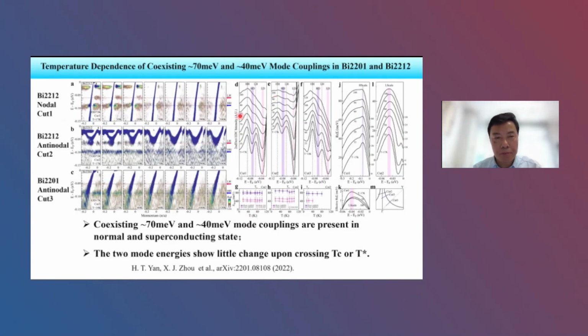Then we come to the temperature dependence. We also did this temperature dependence in Bi2212 and Bi2201 along different momentum cuts. What do we see? We warm up from low temperature to high temperature above Tc, or even above T star, the so-called pseudogap temperature. And we can still see that these two modes above Tc still exist. So the coexisting 70 millivolt and 40 millivolt modes are present not only in superconducting states, but also in normal states, and even above the pseudogap state.